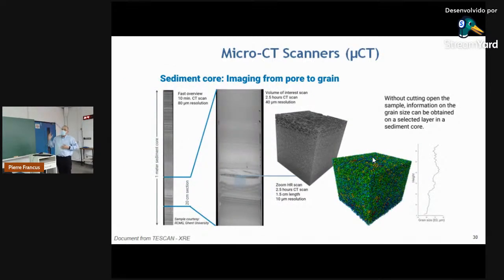So basically, the idea with the MicroCT scanner is to scan the sediment core at low resolution, and then zoom into a region of interest where you can make a 3D reconstruction of the sedimentary fabric. From that, you can do porosity reconstruction, even reconstruct the network. This is of interest, for instance, for carbon sequestration or for geothermal energy potential characterization.